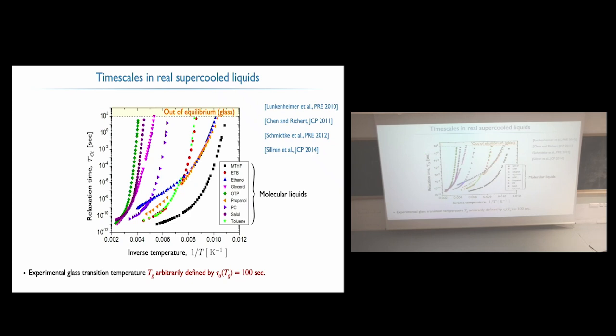So why do we do that? The reason is simple, because if you expect to have a very simple process, which is Arrhenius, so if you imagine that the way the liquid flows is simply overcoming a simple barrier, you would have Arrhenius. So, for the people who are not familiar, exponential of E over T. You would have something like an Arrhenius law. So when you take the log of this as a function of the inverse temperature, you would get a straight line, okay? So that's why we typically represent it that way. It will become a bit clearer afterwards.